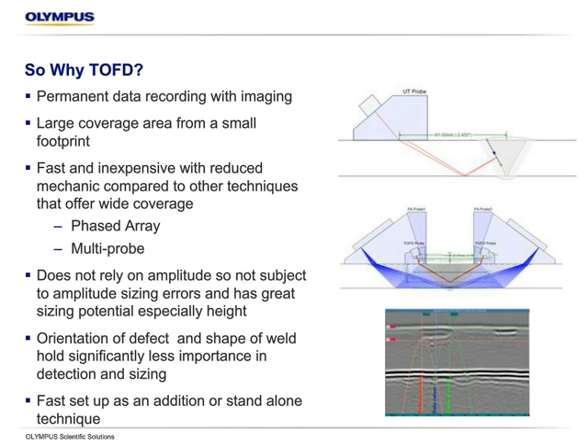Most pulse echo techniques, where we're sending sound at a given angle or multiple angles like phased array, are still somewhat dependent on how that beam is hitting the flaw. If we hit it at 90 degrees perpendicular, like we might on our reference flaw, that would be ideal, but defects can lie in many different angles and planes. With TOFD, it doesn't really matter. If we think back early in the presentation to that diffraction concept, as long as we can hit it with enough energy, it's going to send out sound in every direction. We don't really care about how much. As long as we see it, we're able to pick up on those features like the tips and hopefully put an analysis cursor somewhere and be able to measure them.